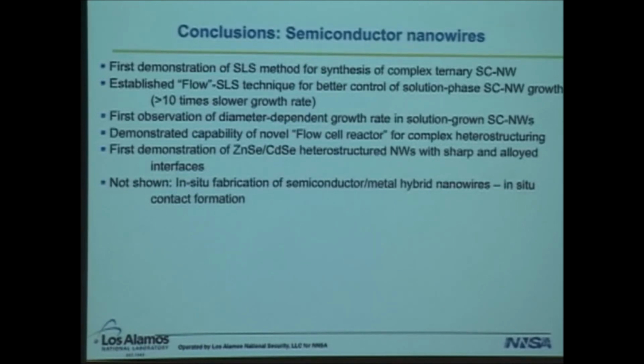And what I didn't show is we also have solution phase techniques to actually fabricate in situ hybrid nanowires. We have semiconductors growing directly off of a metal rod or metal wire. So the idea there is to have established in situ contacts between metals and semiconductors, which, for solution-grown semiconductor materials is a big deal because everything we grow in solution is coated with this fatty layer of organic goop that makes them somewhat hard to contact.